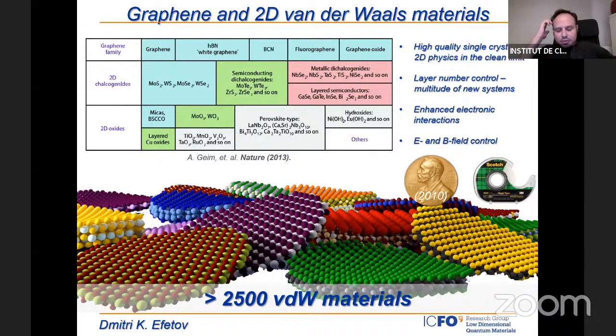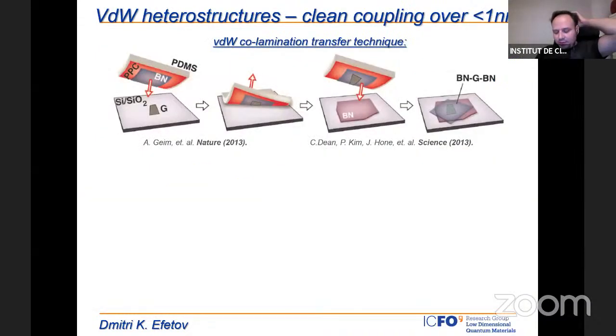And then the other thing which we realized very quickly is that it's really not just graphene and graphite which can be manipulated in this way, but there are a lot of different materials which can be extracted in the single layer. And these really cover all the interesting phenomenology. This includes superconductors, semiconductors, magnets, topological insulators, and so on. The other thing which happened in the field was that we realized that we can build up from these materials. We can extract those two-dimensional layers, but we can also combine them into the third dimension.